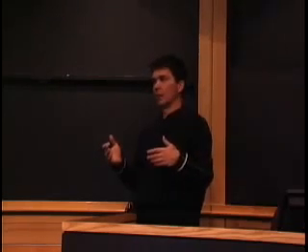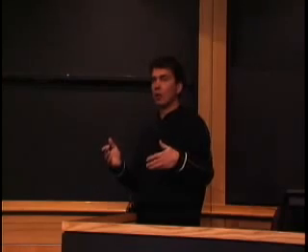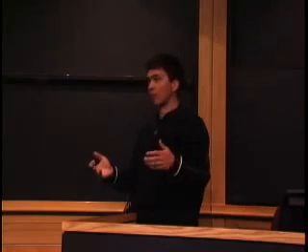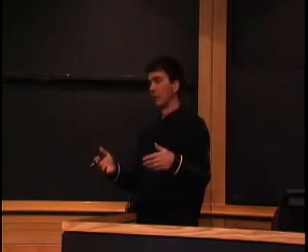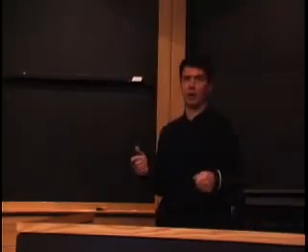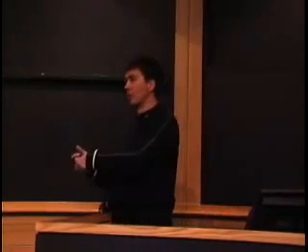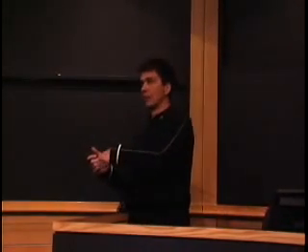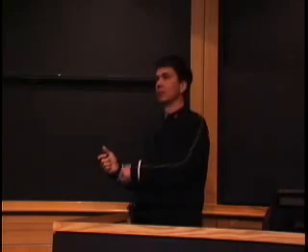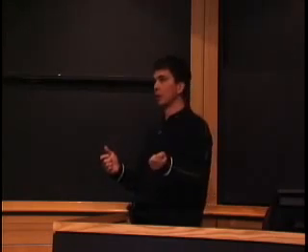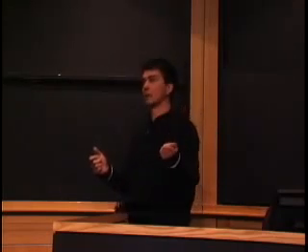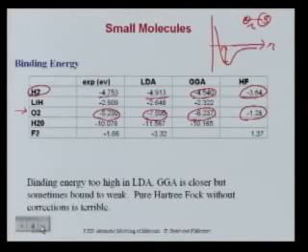The thing is that you will have more error cancellation as the states that you subtract are more physically similar. But the problem is, let's say you look at oxidation of a metal, aluminum plus oxygen going to aluminum oxide. The oxygen in aluminum oxide is very different from the oxygen in the O2 molecule. So not all the error will cancel. Let's say it was so bad that you kept 2 eV error.